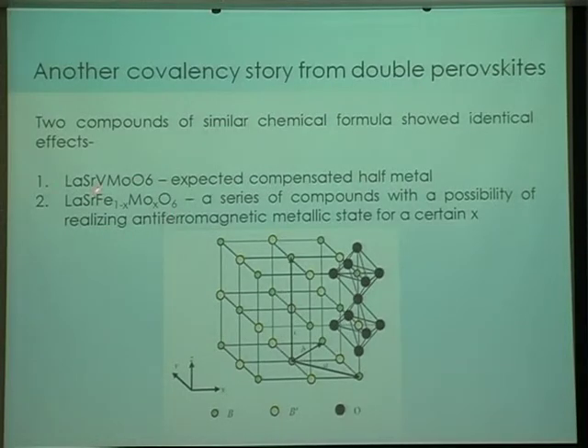In fact, all these compounds, it doesn't really matter. There is only one single phenomenon that's there in all of them, and that's precisely what I'm trying to tell you. Now, this is double perovskite. I'm sure that the seniors here know what double perovskite is, but again, for the students, a small description. This small cube that one can see here is a perovskite cube. At the corners, you have the transition metals, vanadium or molybdenum, the yellow and the green spheres. At the body-centered positions, you have these A-site cations sitting, and at the edge centers, you have the oxygens, making this VO6 or MoO6 kind of octahedra.